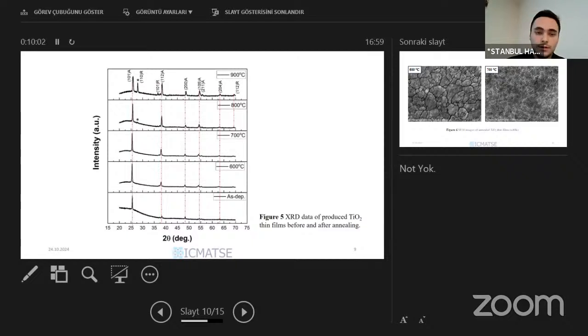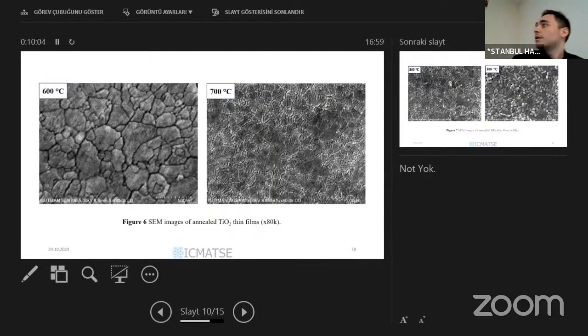Anatase and rutile phases. You can see some SEM images of the TiO2 films here. Grain boundaries and grain size can be clearly seen. For 600 degrees, we have an average grain size of around 50 to 500 nanometers.